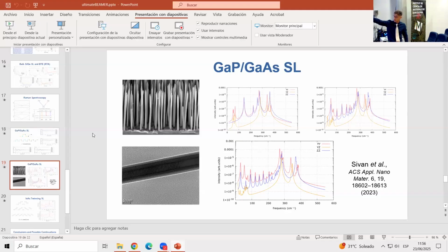Plus, in order to exist, this superlattice nanowire is enclosed into a gallium phosphide shell, and this is necessary, and also the bottom and the top of it are made of gallium arsenide, otherwise it cannot exist in nature. I mean, we know how to grow the superlattices, but only inside a sort of shell of gallium phosphide. So when we perform the experiments, there are many sources of minor modification to the spectra. I would assume that if you could really take a bulk superlattice in the experiments, with perfectly flat interfaces and perfect periodicity, and measure the Raman spectra, it would match pretty well our predictions.